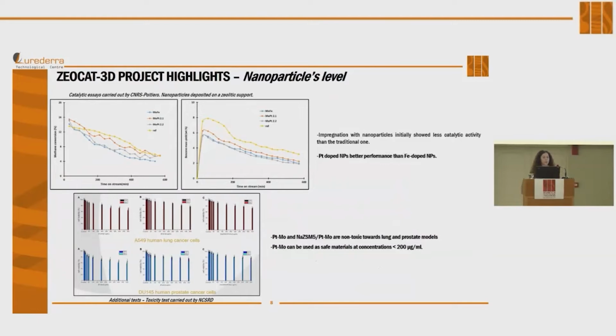Okay, so now I would like to mention some highlights of this project. First of all, as I've mentioned, we finally selected the platinum molybdenum nanoxide as the dopant, as it has a better catalytic performance than the iron doped nanoparticles. Also, Democritus carried out some toxicity tests in which we saw non-toxic behavior towards lung and prostate models, and also that this nanomaterial can be used in a safe way, I can say, at concentrations below 200 micrograms per milliliter. So these are some relevant results that we can mention.